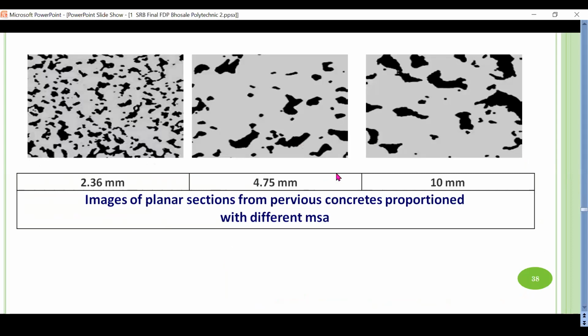So you can see here a microstructure of three different size aggregates. One is 2.36 mm, another is our fine aggregate 4.75 mm, and the third one is 10 mm aggregate size. These dark areas, these black spots, are voids. Now, if we quantify all these voids, it is found that for each sample it is around 20 to 25%. So the void content is the same, but the pore size is different.